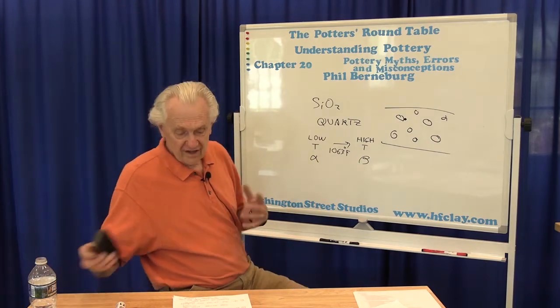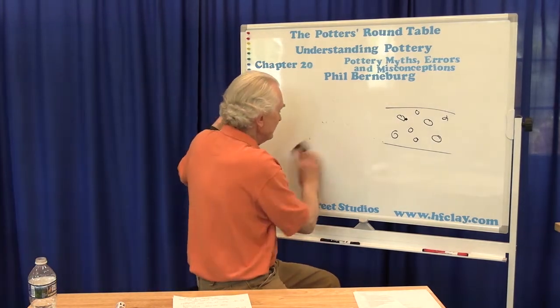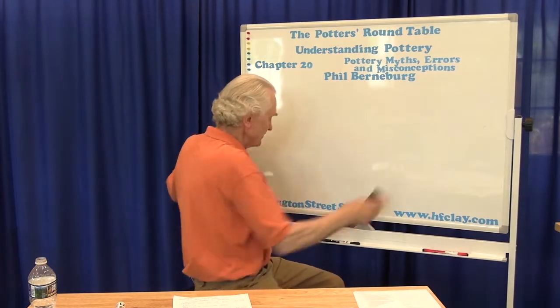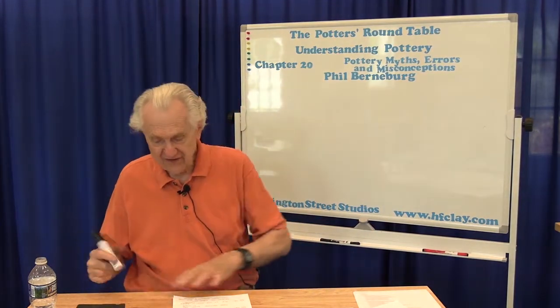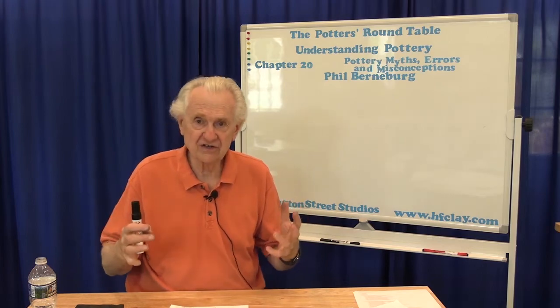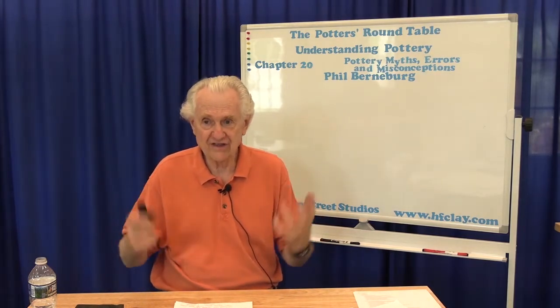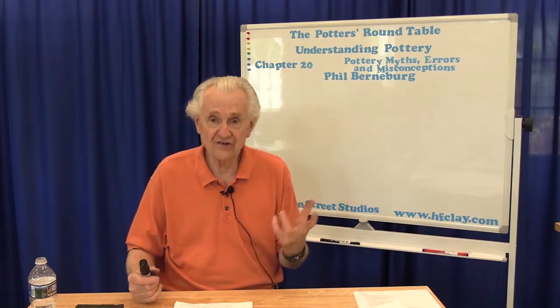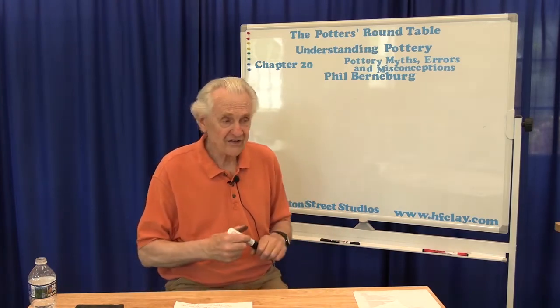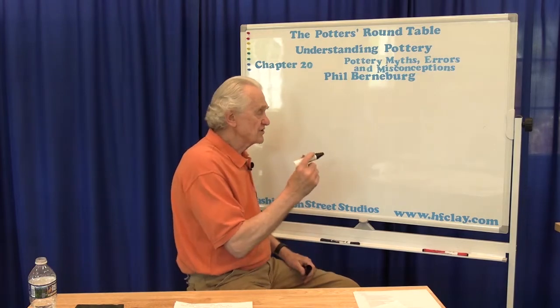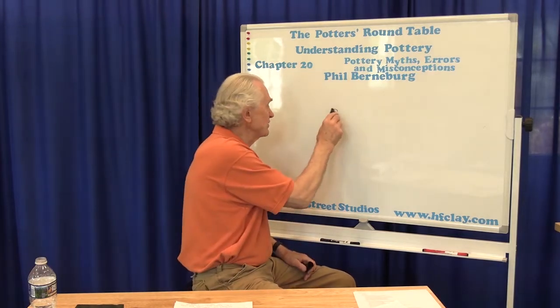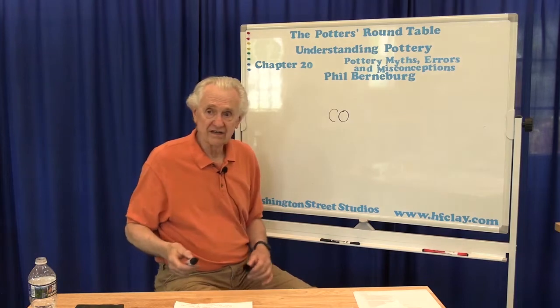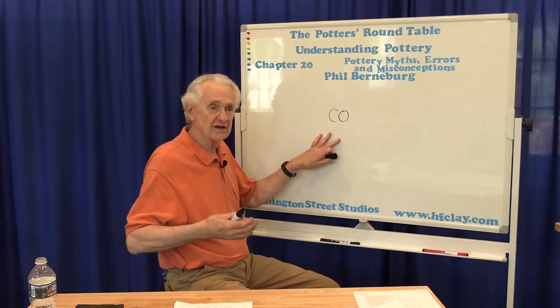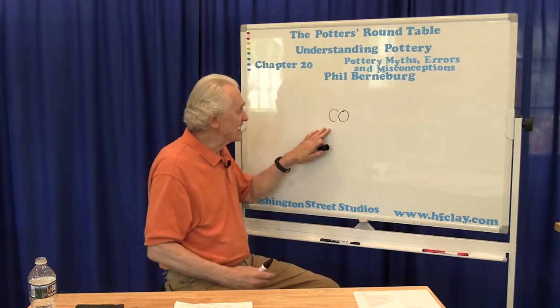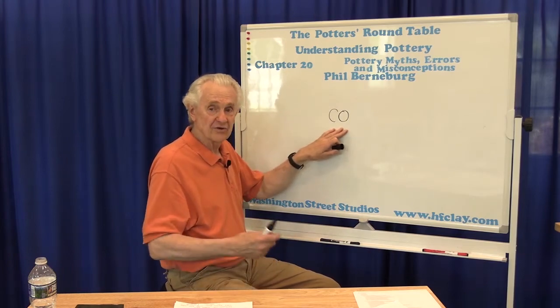Okay, another item related to firing, especially reduction firing, so gas or wood, especially gas, is that when you're putting the kiln under reduction and you want to keep it in reduction, making soot is a good thing. That's a good sign of reduction. Well, it's a good sign of over-reduction. Because as we've talked about before, what you really want to do, and you can't see it, is make carbon monoxide. That's what you make when you don't provide quite enough air to burn the fuel completely. And it's the carbon monoxide that's doing the reduction.